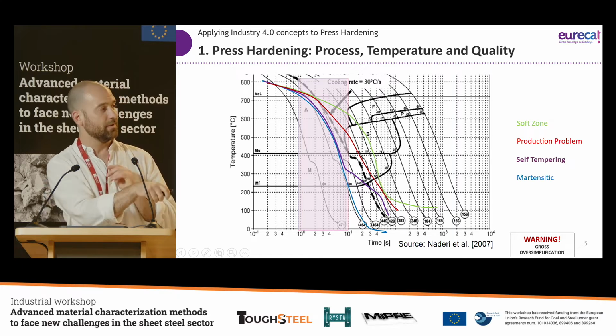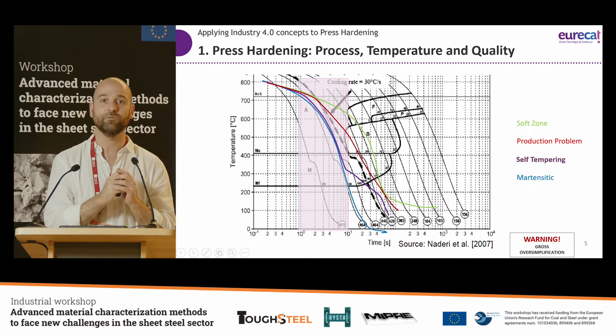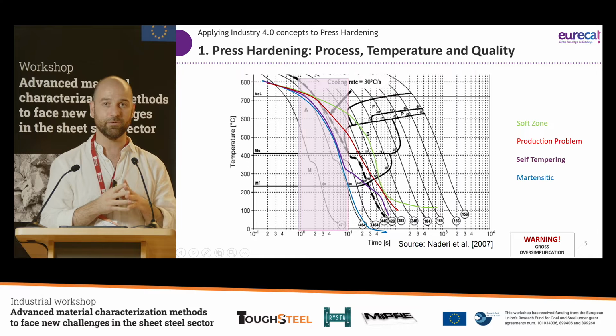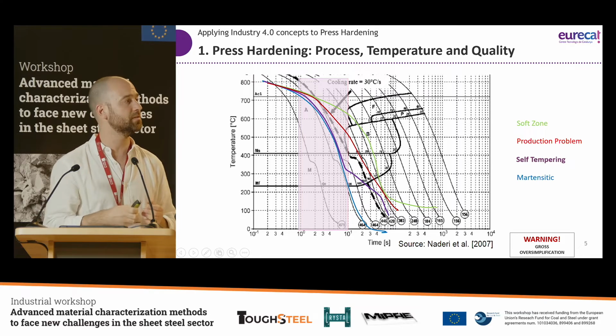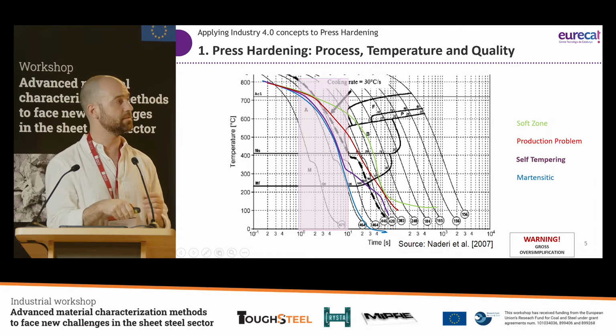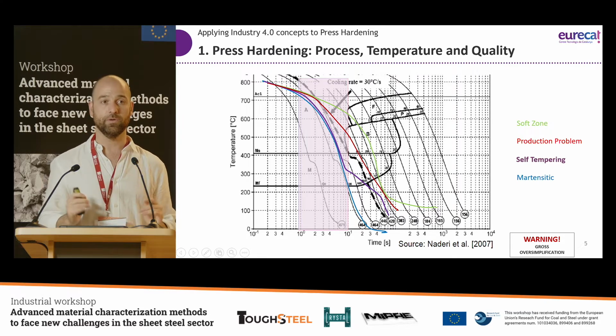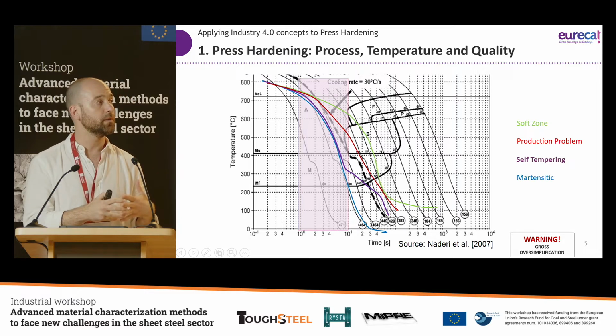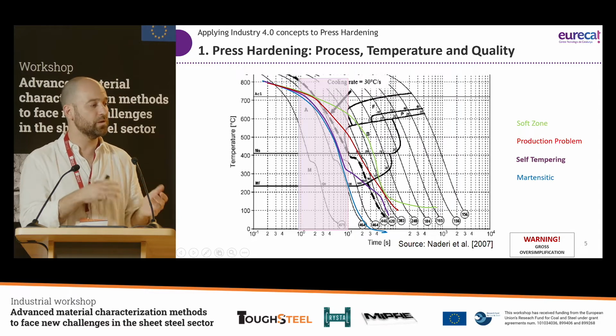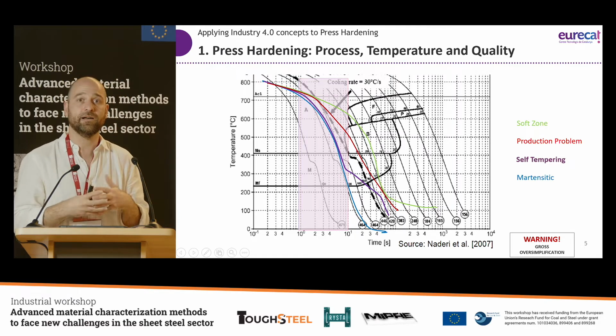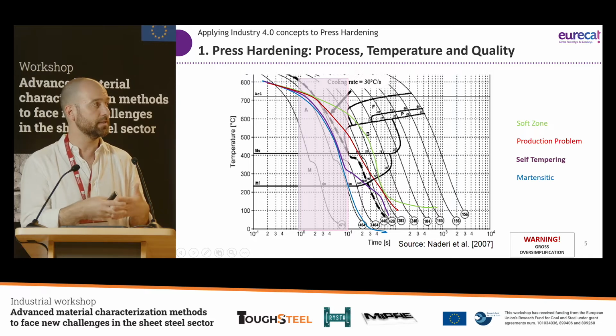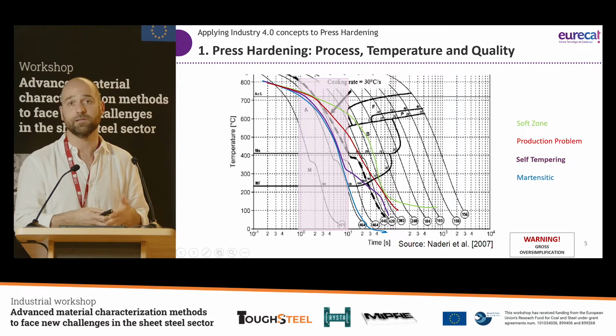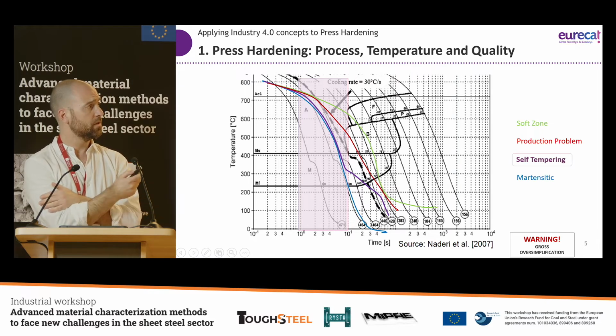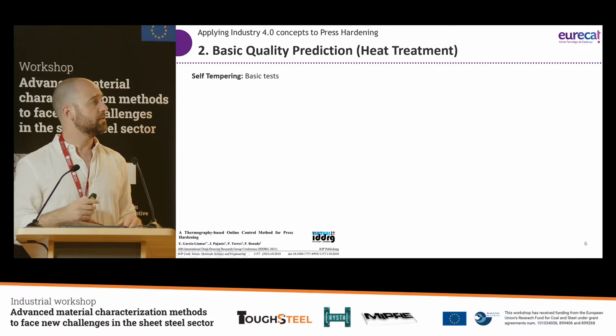And please, this is a gross oversimplification, and when Carlos speaks afterwards about MIPRE, we will see that there are much more nuances to that. But basically what we can see is that if we open the die with a piece that is too hot, the transformations will somehow be interrupted, and we can have self-tempering. So this martensite that we are forming will be tempered martensite. So let's talk about this.